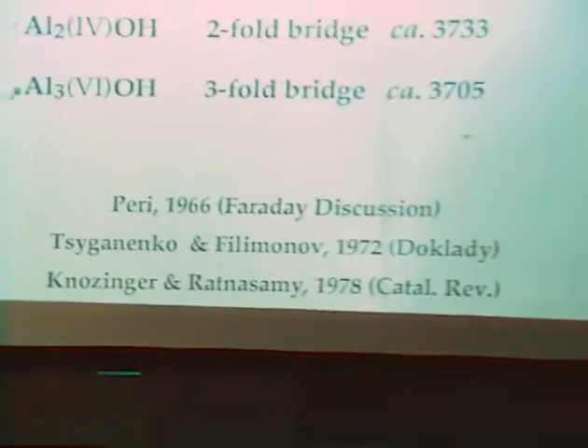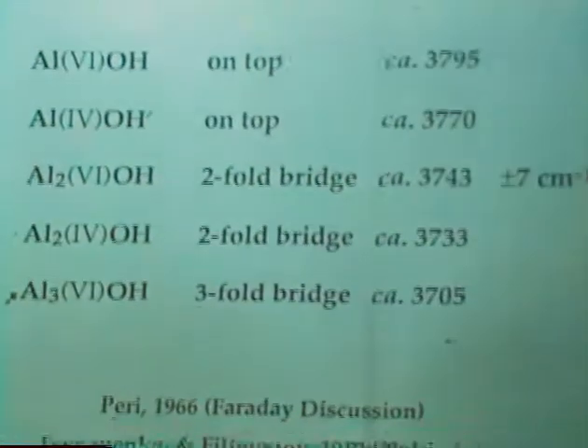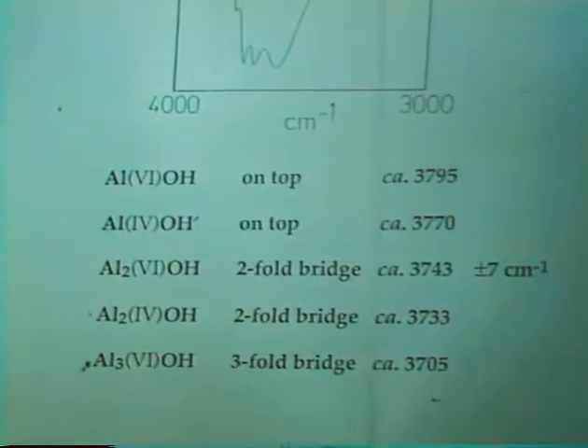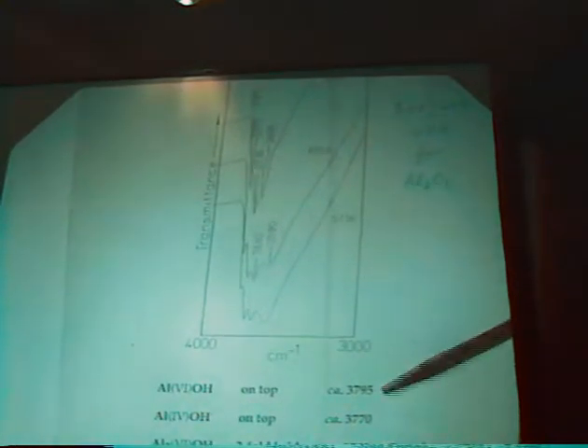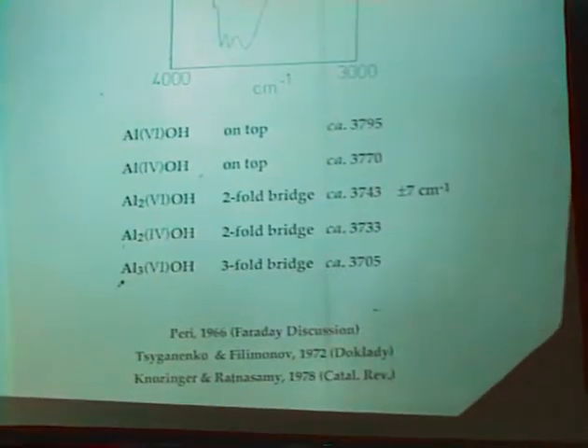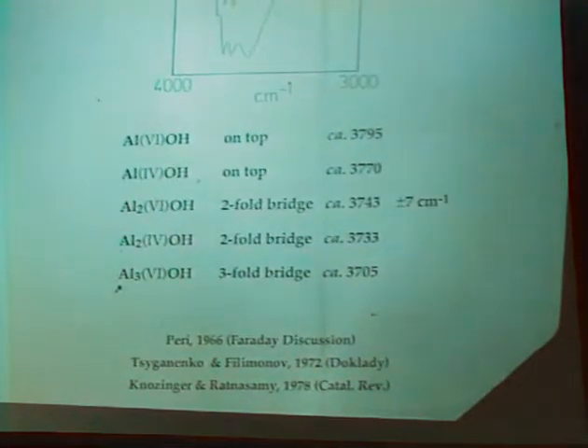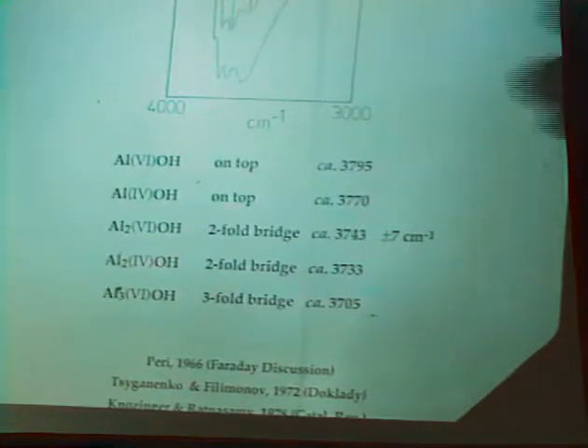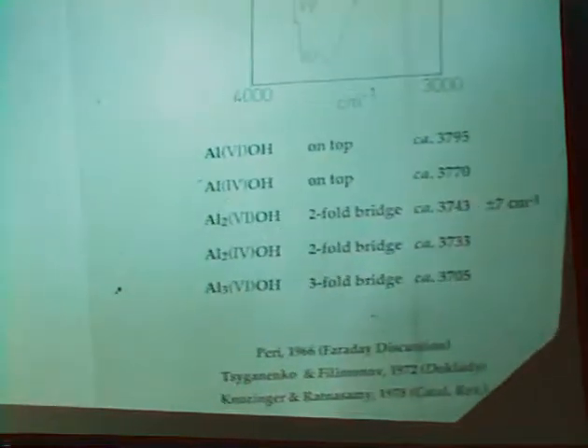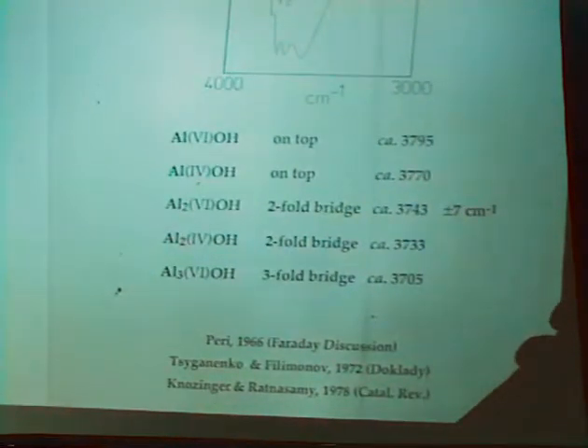This is a spectrum from a high area alumina, where you've got multiple OH groups. And John Peri was the pioneer who tried to assign these to different sites of different OH groups on the surface, such as on top, two-fold bridge, three-fold bridge, and so on. These assignments actually were more recently from Tsyganenko and Filimonov in Leningrad, and I wouldn't know which is right, John, but that just reminds you that this can tell you a lot about the nature of the surface, which of course varies with temperature of calcination.